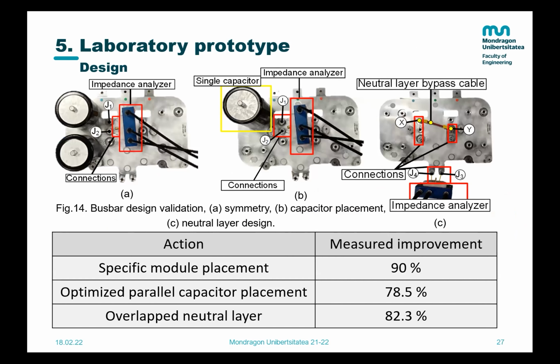We tested our design, measuring the impedance with an impedance analyzer, and we saw that with the specific module placement, we reduced the asymmetries in the current path 90%. With the optimized parallel capacitor placement, we reduced the inductance of the capacitors nearly 80%. And with the overlapped neutral layer, we reduced the inductance of the switching loop over 80%.